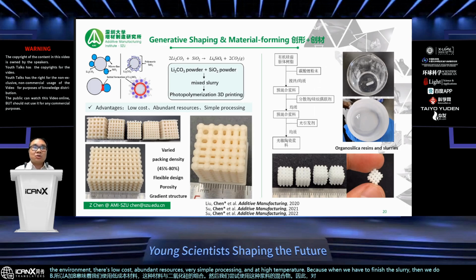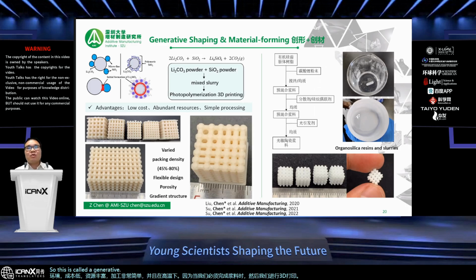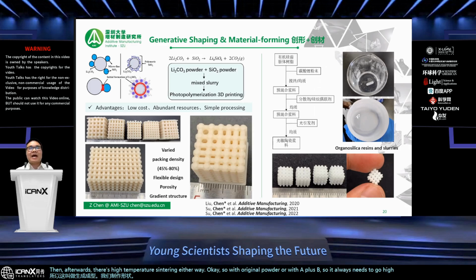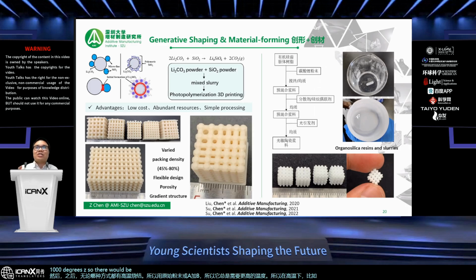Okay, so this is called generative shaping. We make the shape. Then afterwards there's high temperature sintering either way. With the original powder or with the A plus B, it always needs to go to higher temperature. At high temperature like 1000 degrees C, there will be a generation of lithium orthosilicates. So this is a very good strategy that allows us to get very quick and low cost processing.